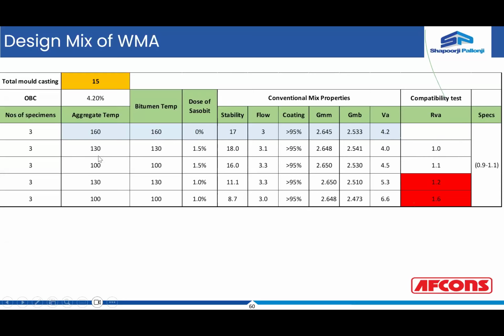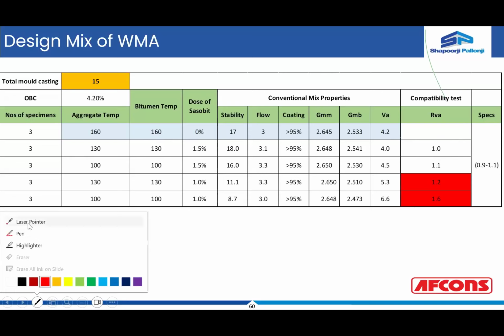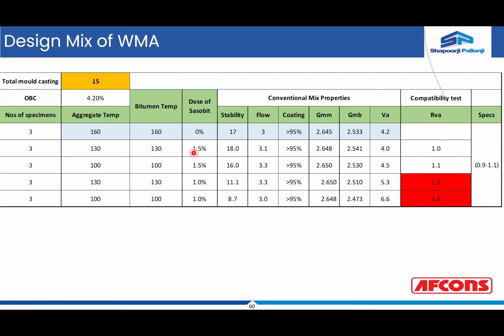Now you have reduced the mix temperature to 130, and the doses of the additives as 1.5%. Now, this dose of additives of 1.5% is resulting in air void of 4%, wherein it is giving you a ratio of 1, which is in line with 0.9 to 1.1.